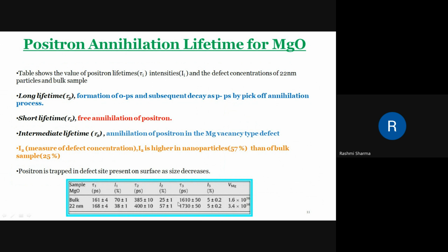This longer lifetime tau 3 corresponds to the formation of orthopositronium and its subsequent decay as parapositronium by the pick-off annihilation process. The shorter lifetime, tau 1, is because of the free annihilation of positrons. The intermediate lifetime, tau 2, is because of the annihilation of positrons in the magnesium vacancy type defect.